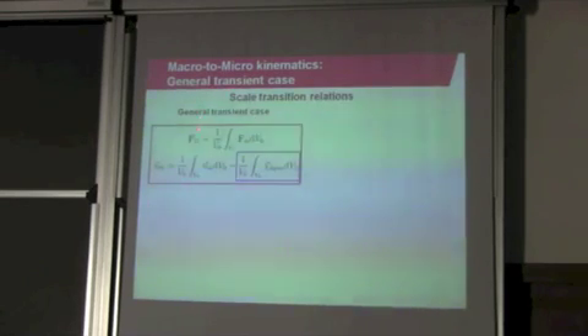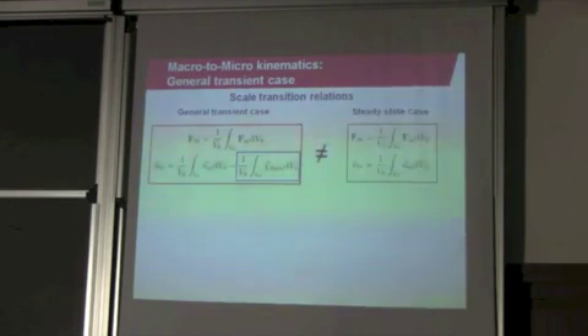And this is actually what they are. So the first one is, again, exactly the same as in the quasi-static case, nothing special here. The volume average of the microscopic deformation should give you the macroscopic deformation. Now this one, for the displacement, is somewhat trickier. And that's in fact what makes the whole trick for this local resonant metamaterial.